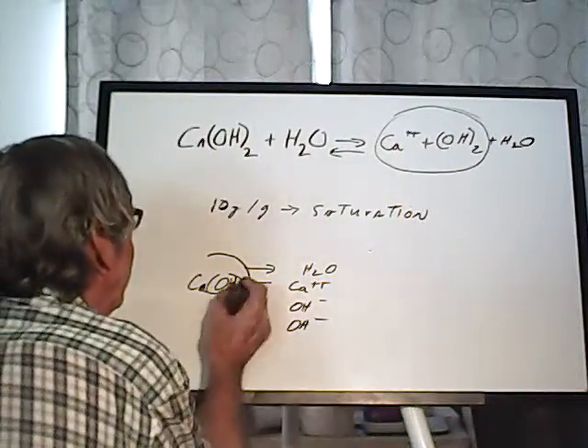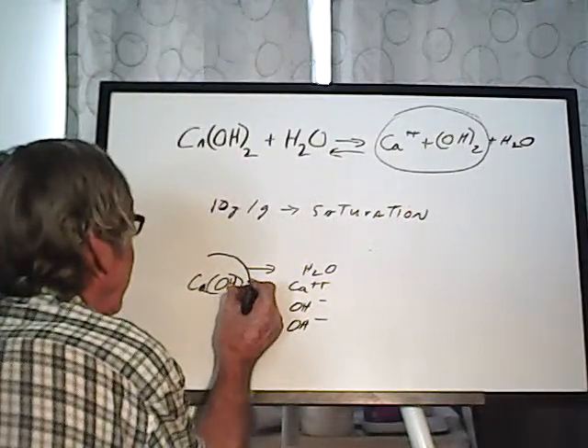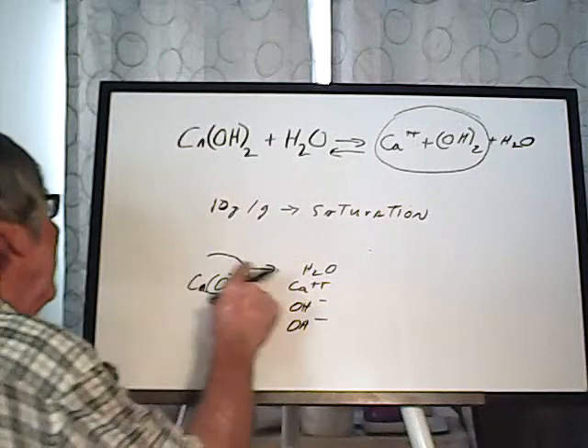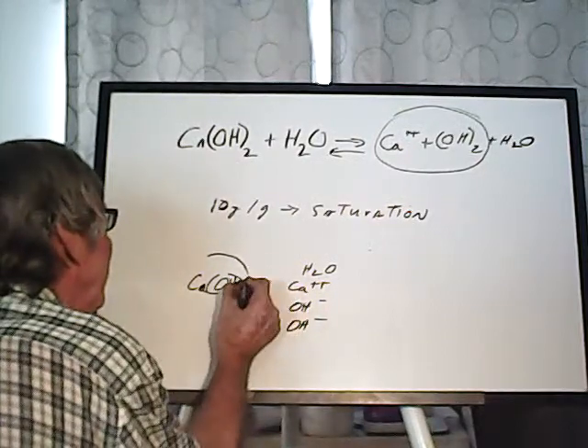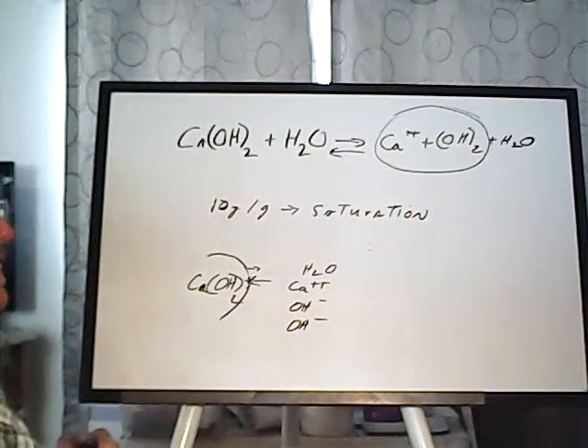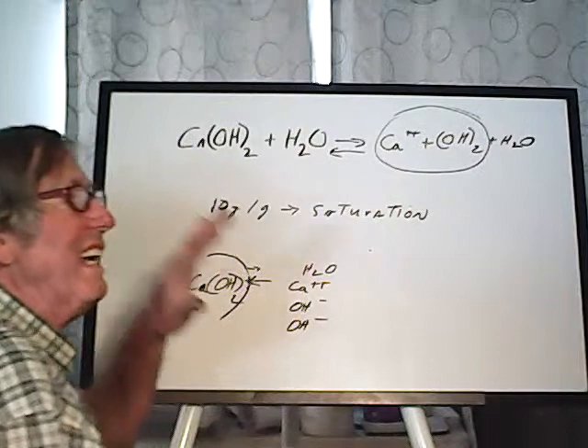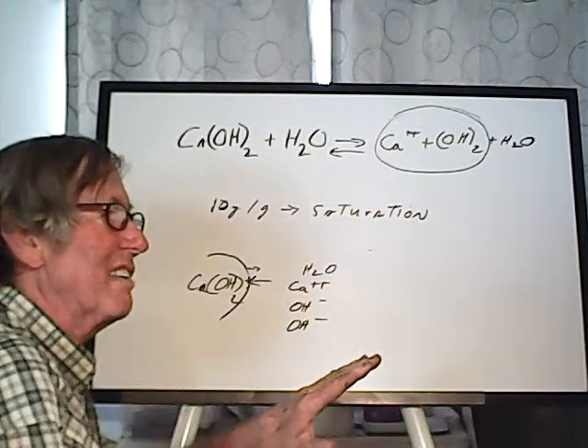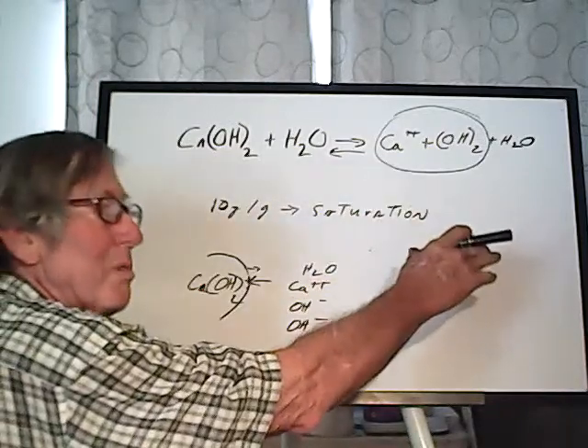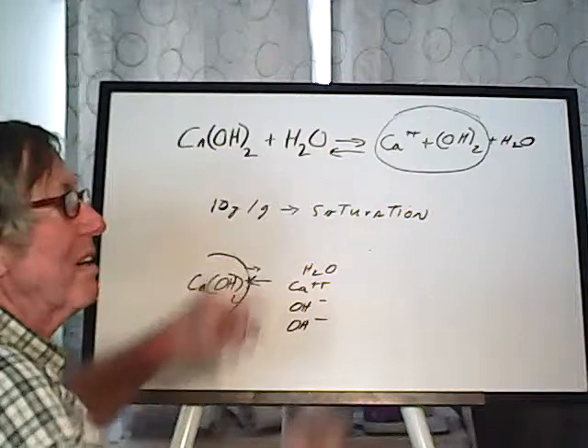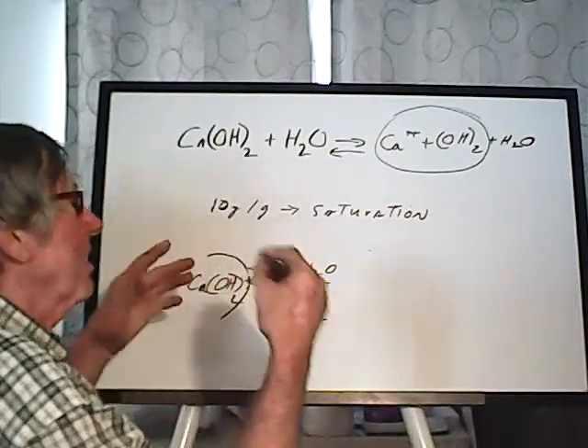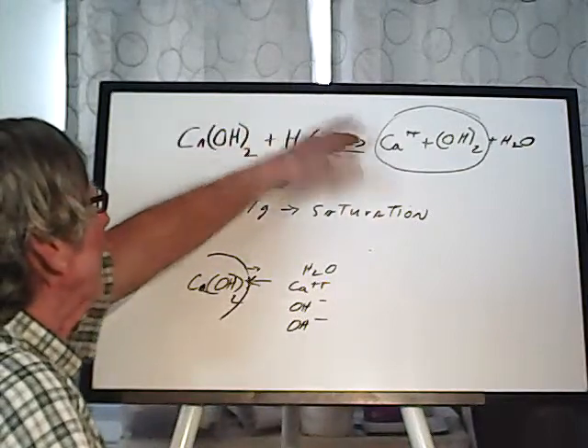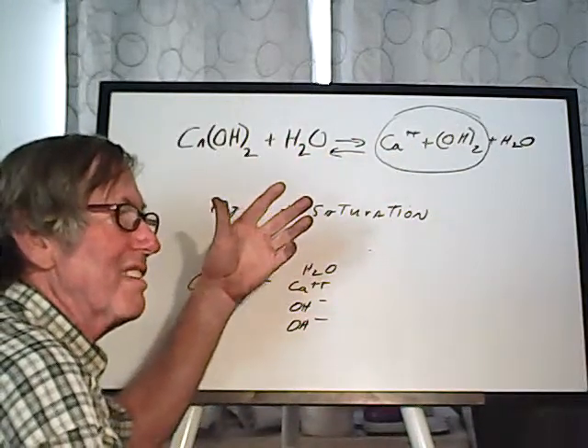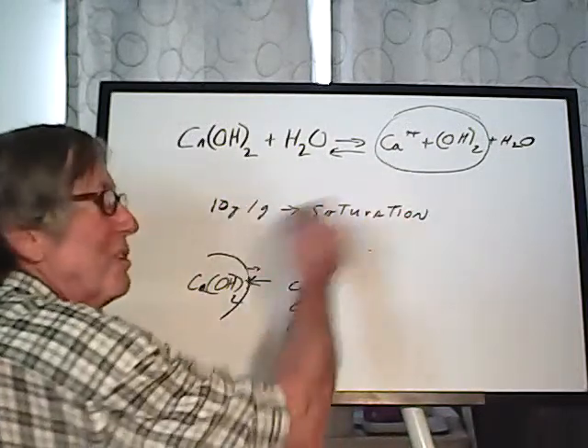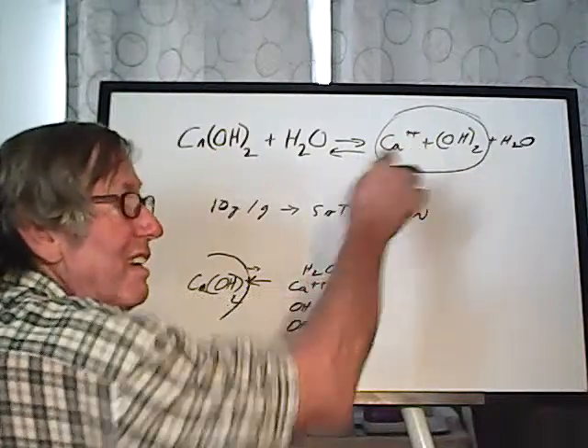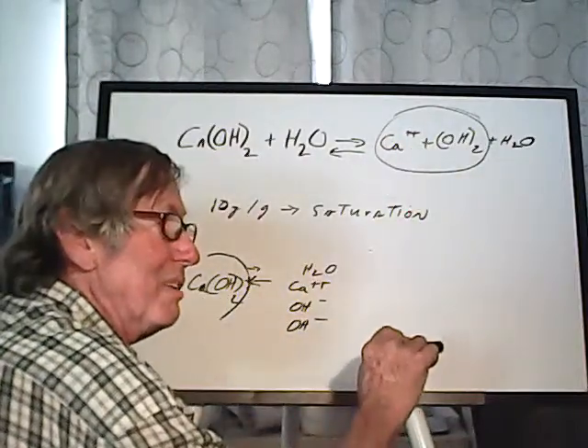If you add more water, then that isn't being pushed as much. If you dry it out, then the equilibrium goes the other way. In most chemistry, it's equilibrium reactions. You have very few reactions that are 100% one way. Most of them, there's a balance that occurs. When you mix calcium hydroxide, it'll only take it to about a pH of 11.5. There's a reason for that. Because at saturation, there's only so many hydroxide radicals floating around. Sodium hydroxide is much more soluble.